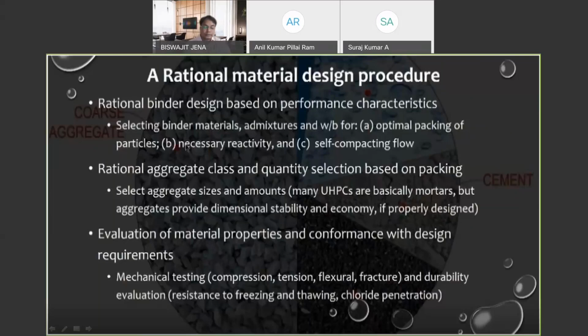Then you have to ensure that the particles are packed really well, not just packing, but you have to ensure that they are reactive enough also. So what is mostly reacting in our system initially? It is the cement and all the other materials that you put in and helping cement to do its job. For example, if you put in silica fume at very early ages, which acts as nucleation sites, all those materials are helping cement, which means you have to put those in a volume and ensure that they are distributed enough for the cement to do its job.